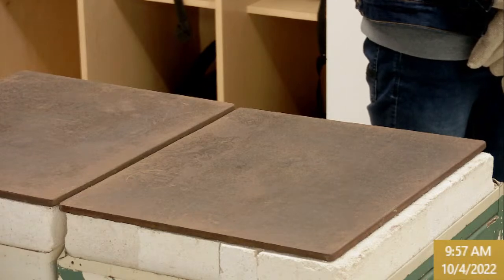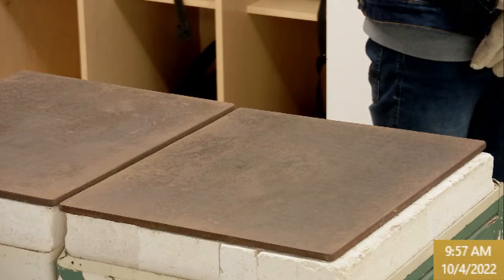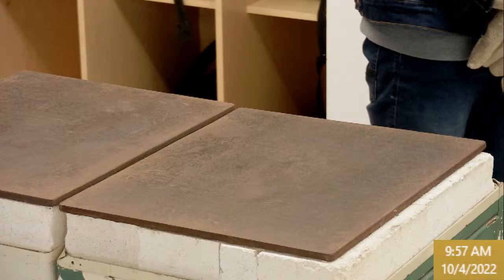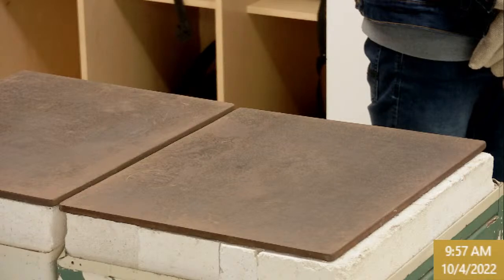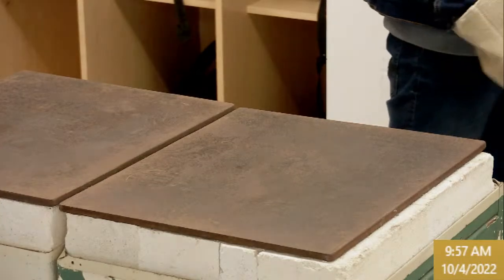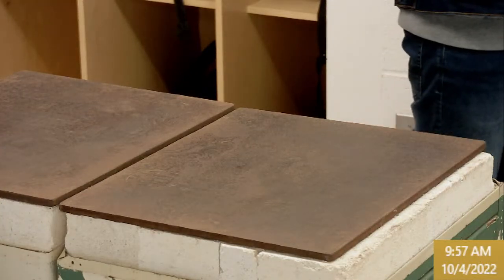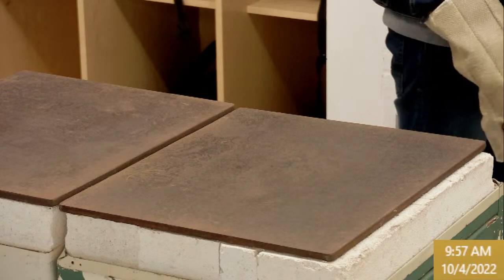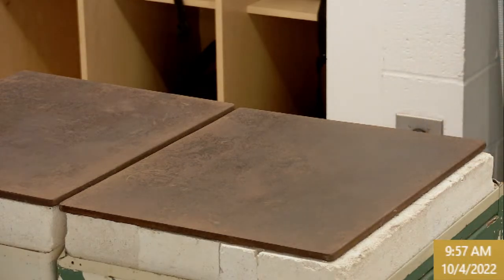Silica Beach Sands. This is the Lake Michigan sand. We've got 2.5 grams of aluminum oxide, 50 grams sodium carbonate, 26.8 calcium carbonate, and 0.49 grams of copper oxide. So batch A, and we're pulling from the front left. All right, so here we go.